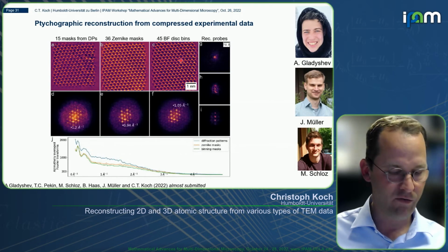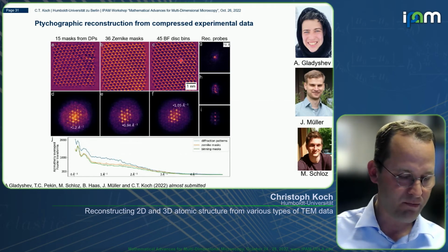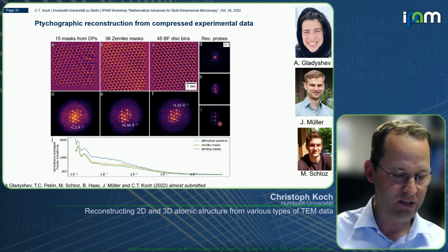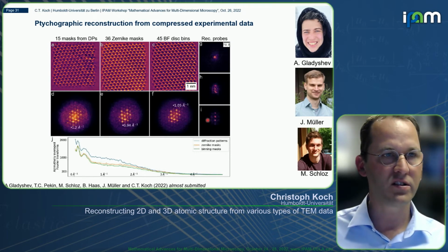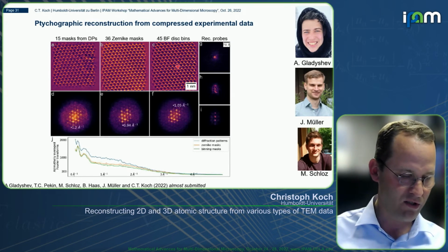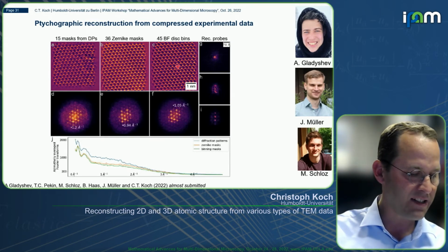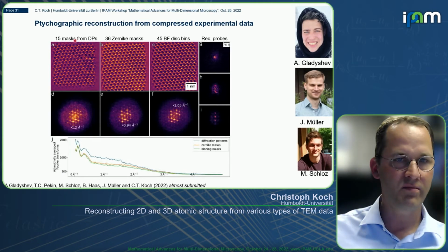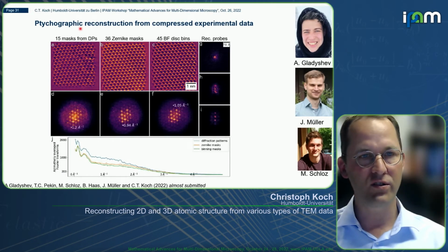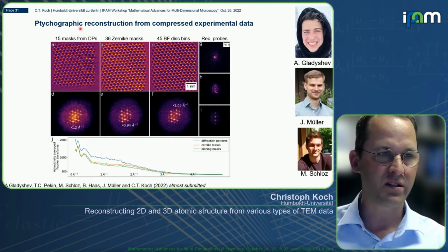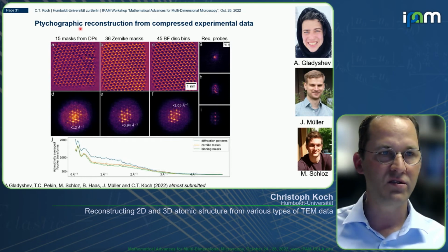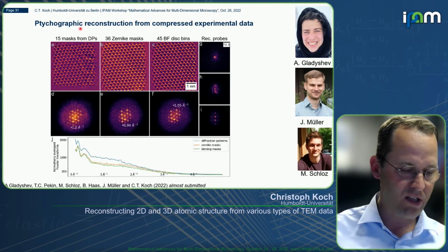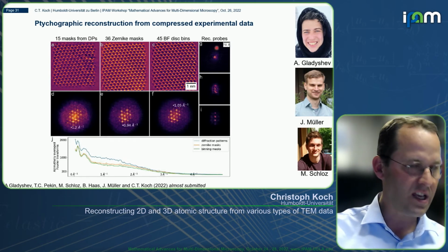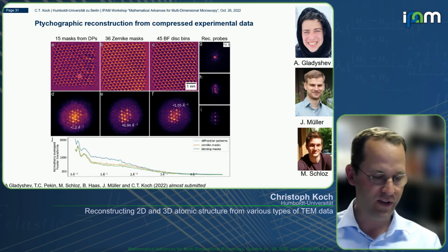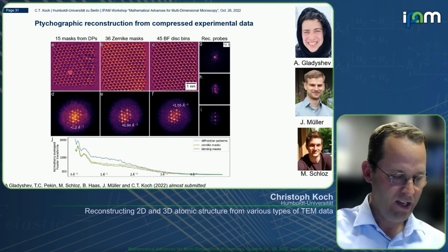That means low spatial frequency information was missing. Also the probes, this probe corresponds to this reconstruction. This probe here, which clearly contains specimen information, corresponds to this reconstruction. So that didn't work so well. But if you really apply masks that are based on just sampled diffraction patterns, so before you do your experiment, you just sample a few diffraction patterns, you orthogonalize them and use these as masks, the probe also gets reconstructed very nicely, in addition to the sample reconstruction being much more faithfully retrieved.